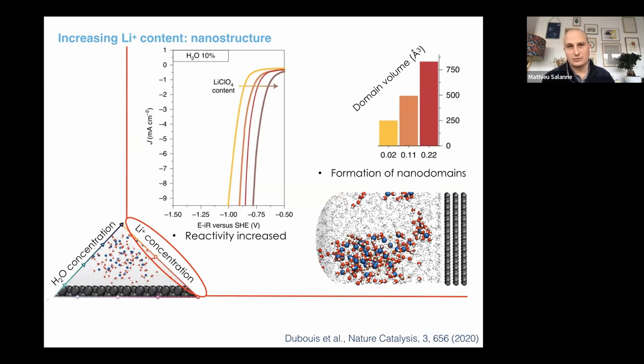This is quite famous for water acetonitrile mixtures, but it's even increased by the salt. So the salt is playing the role of glue because it really wants to go inside the water, and so it will attract the water, and you end up with a biphasic system. I did not show it here, but we also had some SAXS, small angle X-ray scattering experiments that also show this nano patterning.